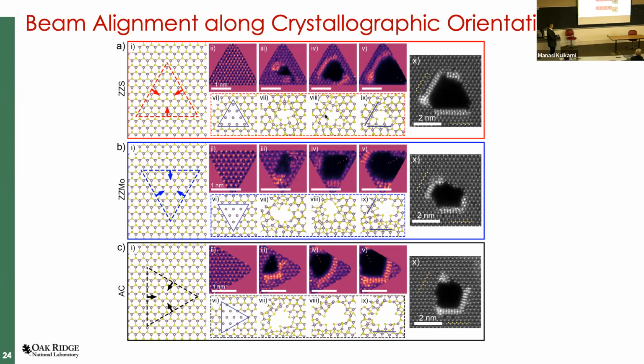How does that result in your end product? The idea is we wanted to create a nanopore bounded by those metallic and even ferromagnetic atomic edge structures. For what application in the future, I don't know, but it was just really cool to see that. So this is the most important thing that we came up with. A high percentage of the time when we were cutting along this direction, we would kick out the sulfur atoms because that was a terminating group. Then you have this local enrichment in molybdenum, and then you can create these structures that we saw during the thermal treatment process. So we thought we had something pretty cool here.